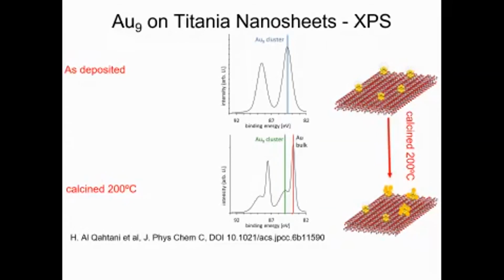We still have remaining, even after annealing, some isolated Au9, but we also have aggregation of Au9. But for sure, we don't have any phosphorus left, which means the ligands containing the phosphorus are detached from the Au9 nanocluster.